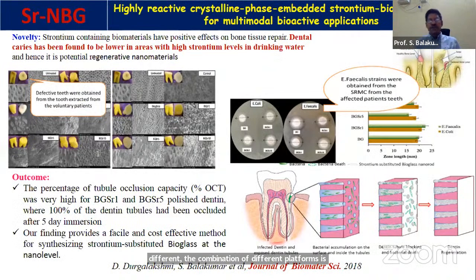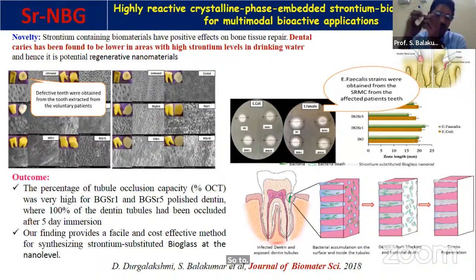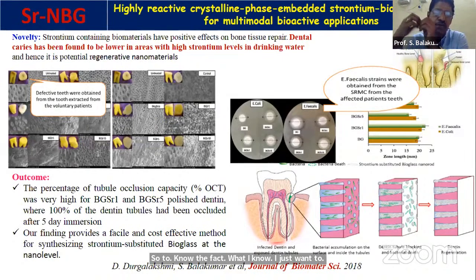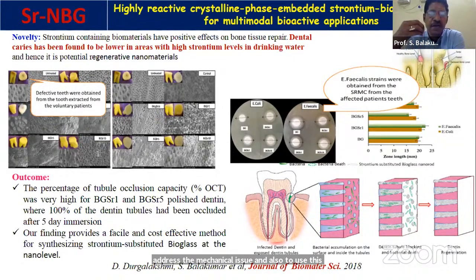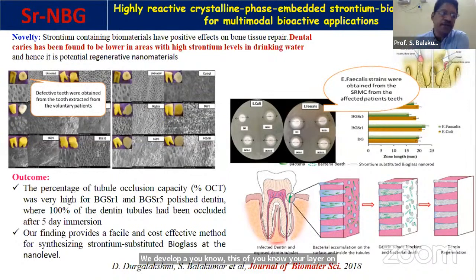So the first work I just want to share is this: in order to address the mechanical issue and also to use this material for dental remineralization, we have substituted the calcium with strontium at different ratios, and we systematically studied the material. We found that when you incorporate 1 to 5%, that certainly enhances the dentin tubule occlusion capacity of the material. Within 5 days of mineralization, we are able to close this, and we develop a layer on the open teeth where the tubules are exposed.